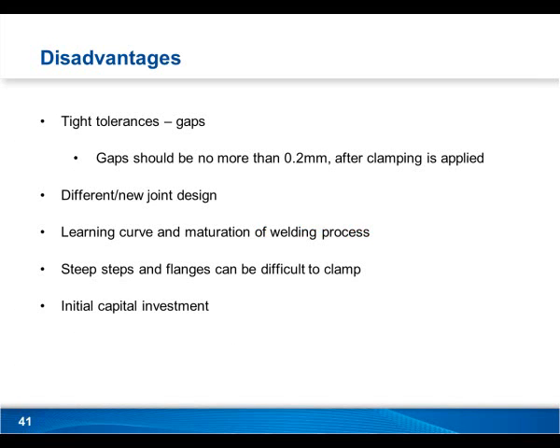So some disadvantages. Tight part tolerances, mostly I'm talking about gaps here. Gaps should really be no more than about 0.2 millimeters. Now this is after clamping is applied, so it's not just the two pieces resting on each other naturally. Once clamping pressure is applied to the part, you shouldn't have more than 0.2 millimeters of a gap. We can overcome 0.2 to 0.4 sometimes, but we like to see no more than 0.2. It just makes your process that much easier.